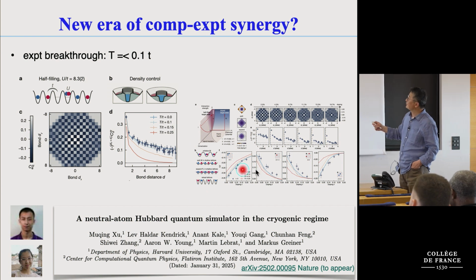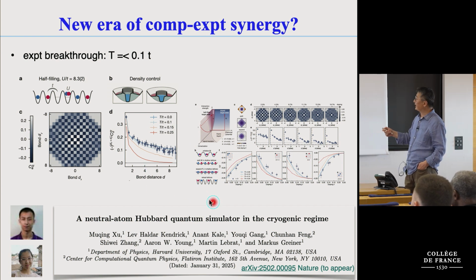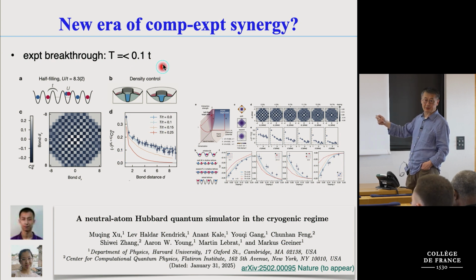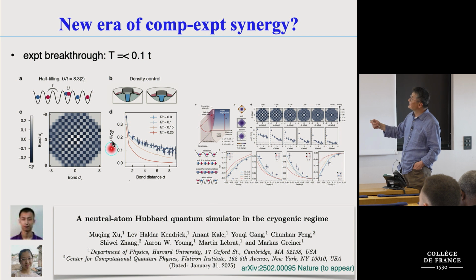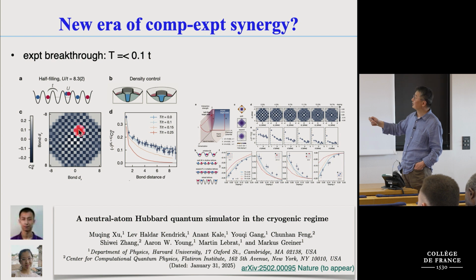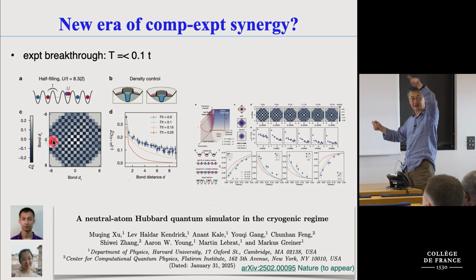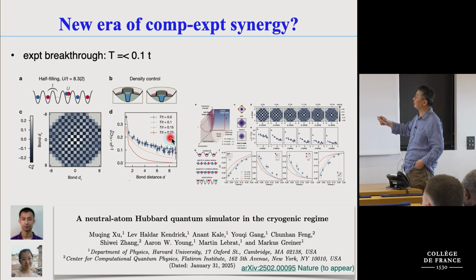Thank you. You saw from Antoine's lecture the latest result from Markus Greiner's group, where the temperature is comfortably now below 0.1. And we know that this is half-filling at a U of about 8, what they measure, the spin-spin correlation function. And this is a line cut, and it's staggered, so it's -1 alternating. That's why if it's plus minus, it's going to now all be positive. And a long-range correlation would be a constant here.